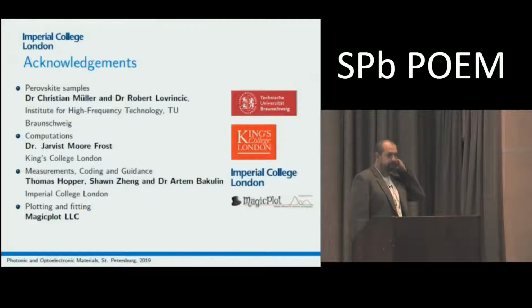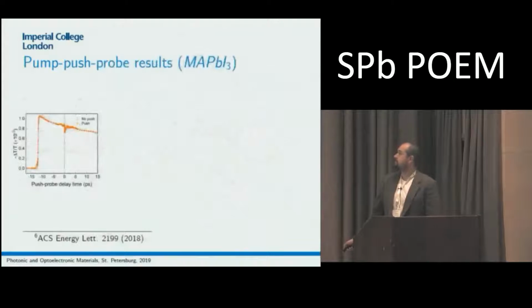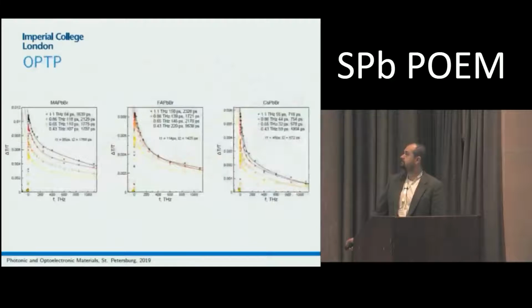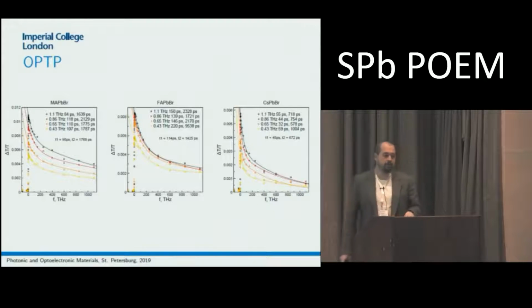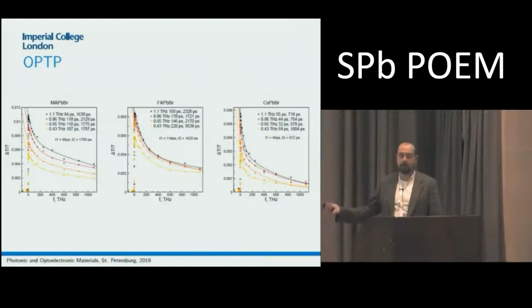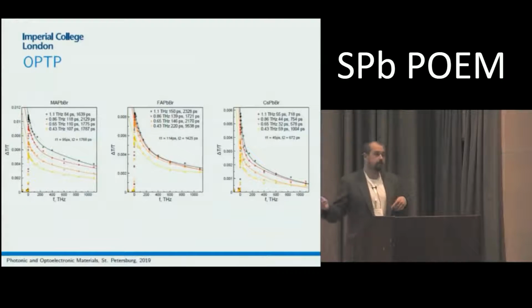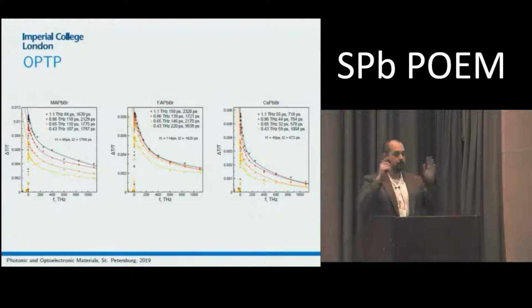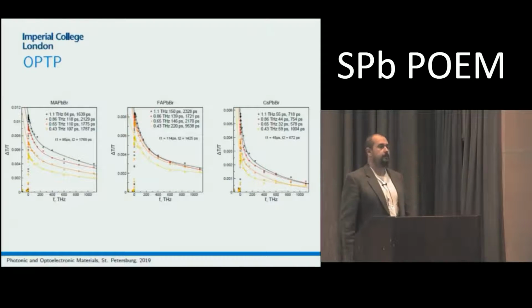In your pump-probe experiments, you observe different dynamics for different, let's say, wavelengths. Did you compare it, for example, to Raman spectrum or terahertz transmission spectroscopy? Because if it's phonon lines, they should be clearly seen there. Yeah, this is what we're looking into now. We didn't do the thorough analysis, but we expect this to be phonon lines associated with phonon interaction, and longer times will be associated with the phonon bottleneck that preserves the carriers from cooling down.